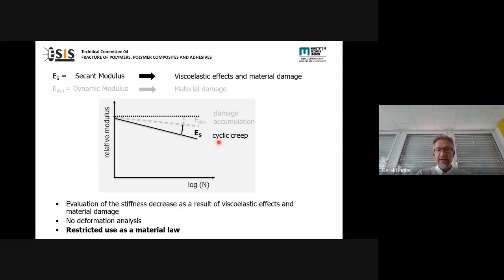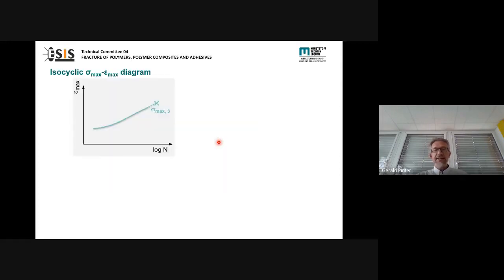So all together, you get a lot more information out of a cyclic test than the Wöhler line if you are able to measure strains and evaluate the stiffness values. But still, you only get stiffness as a function of cycle number. It's only of restricted use as a material law, these data that you get. So in a next step, and this was specifically developed here in our group over the last years, we